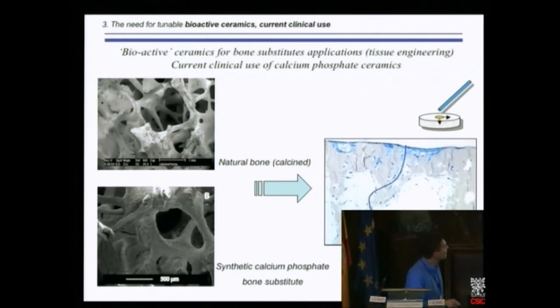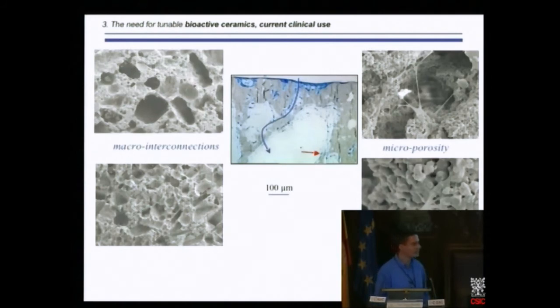So what might be important also is the microporosity, or micro-roughness, you have at the surface of the pores. So an important factor is the interconnection between pores, the macro interconnection between large pores, but also clearly important is to play with the microporosity. What is the roughness at this surface? And what we have seen is that osteoblast cells really like micro-rough surfaces. So here is an osteoblast, which was observed under environmental scanning electron microscopy. And you can see this osteoblast hanging onto the microporosity. I'm not a biologist at all, but when I see that, this is the cytoplasmic extension. It's like the arm of a climber that tries to attach to the surface.